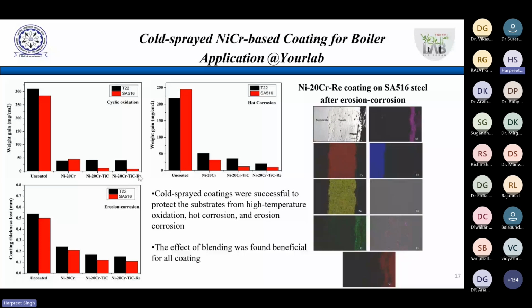So all this mess has to be stopped. So for that, we have introduced this harder phase into the coating. The good thing is that we can deposit very nice thick coatings on our boiler tubes. If you see the cross section of this boiler tube material, this is the substrate, this is the coating. You see how dense a coating we have produced through the cold spray process, right?